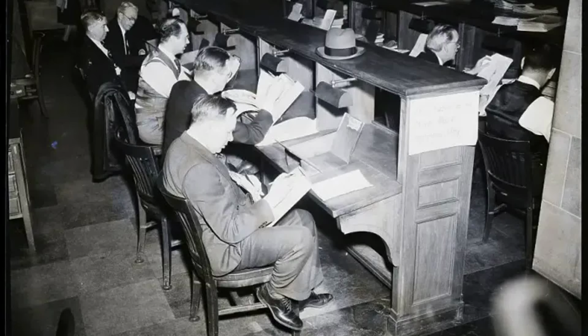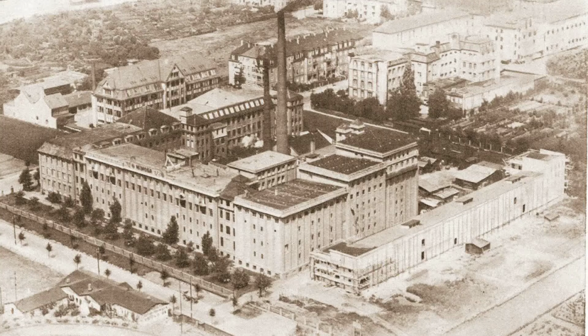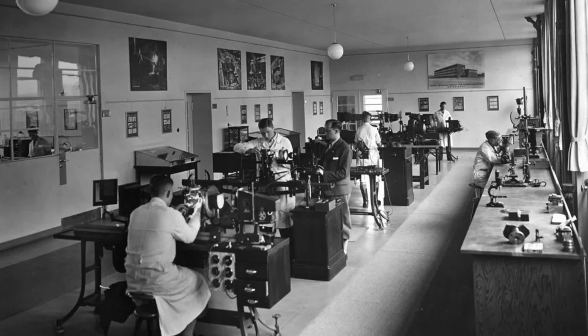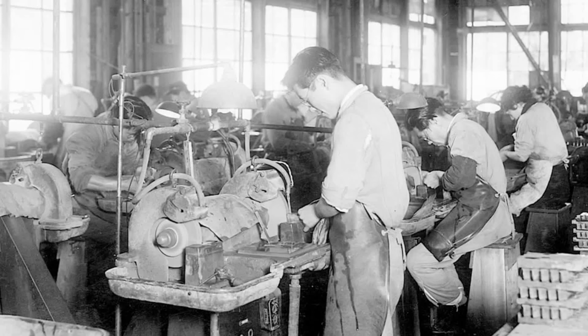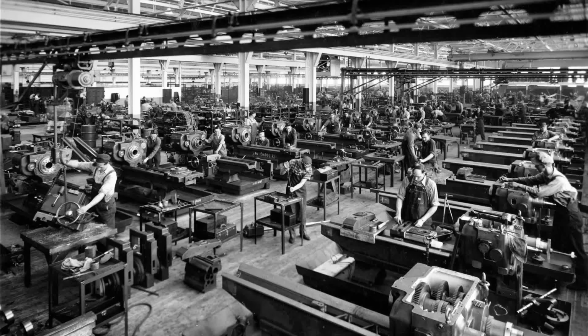One of the most revealing accounts appeared years later in federal court testimony. GE engineer Samuel Hoyt recalled investigating the German material after seeing it at the Osram plant in 1925. The manufacturing process, he concluded, was inadequate for what GE wanted. The carbide could be extraordinary, but it was not extraordinary every time. GE's lamp operations had tested German material and found enormous variation in wear performance. According to the testimony, roughly 1 die in 20 might greatly outperform the material the company was already using. The other 19 could be so inconsistent that the factory preferred its older dies.